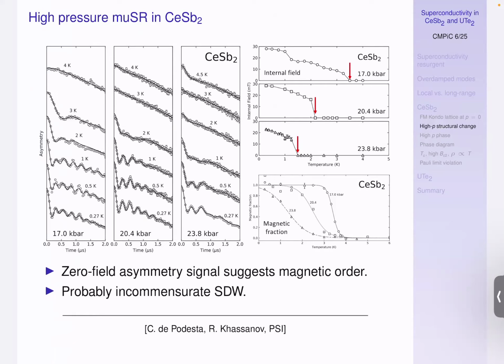You do mu-SR relaxation measurements, which was done at PSI under pressure with de Podesta and Khassanov. You find that on cooling, you get a signature of magnetic order, where the data have a change in decay. And so you can see, all right, at 17.0 kbar, there's this onset of magnetic order, and that onset shifts to lower temperatures at higher pressures.